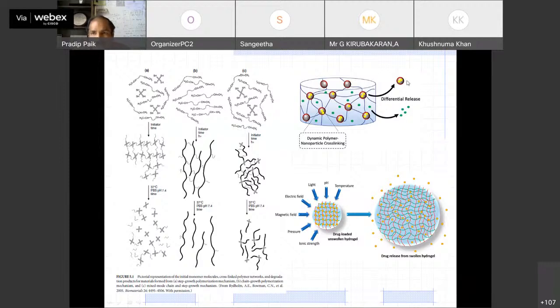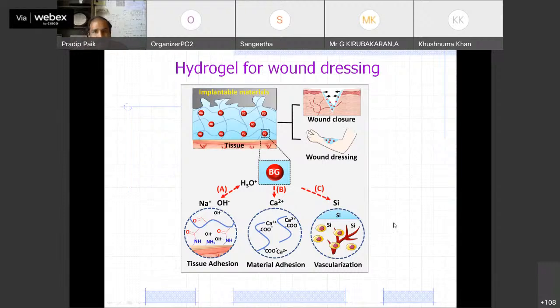Now there is a different method. These nanoparticles you see, there will be a multifunctional core inside, and this core will be inside the network, which forms the hydrogel network. So inside the core you can load the medicine, and inside the hydrogel also. If drug molecules are in the hydrogel, there will be a differential release. And if a second drug molecule is inside this core, it also will be released, and you can stimulate them. How can you stimulate? I have already told: light, temperature, electric field, magnetic field, pH, ionic strength. Everything can be there, so they will be released.